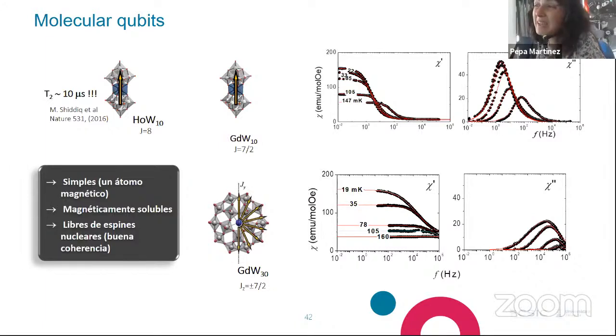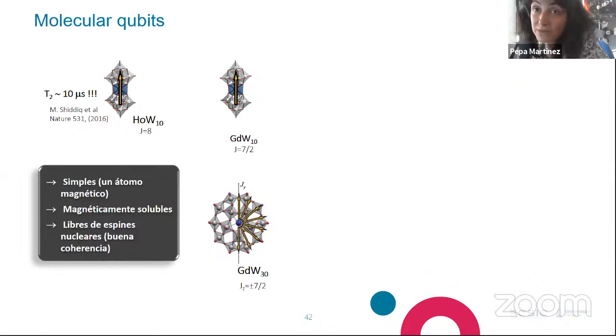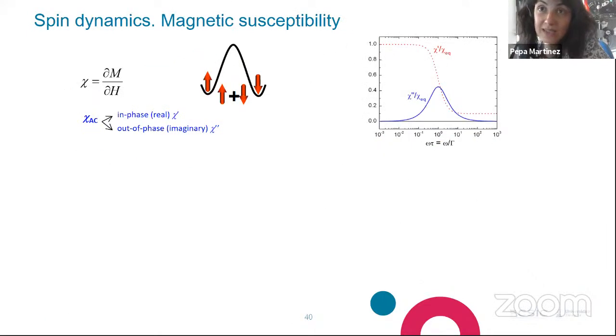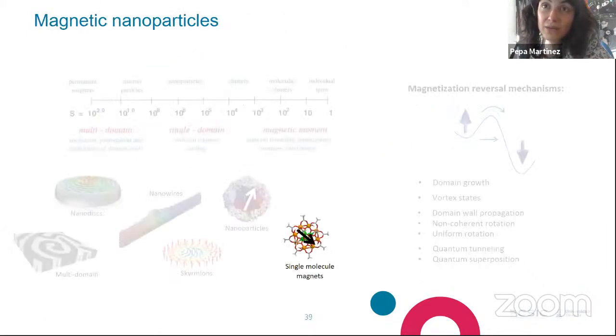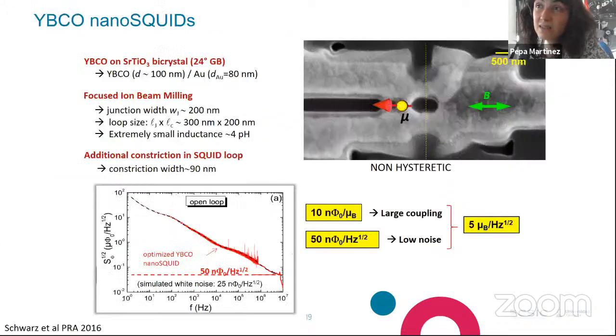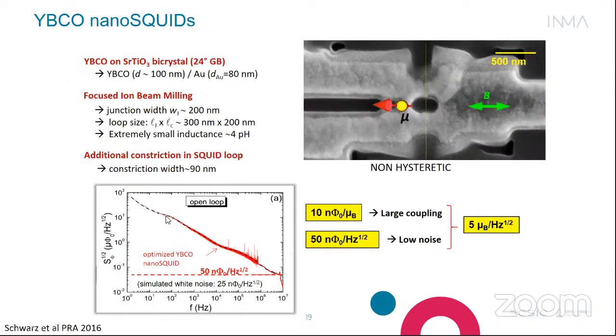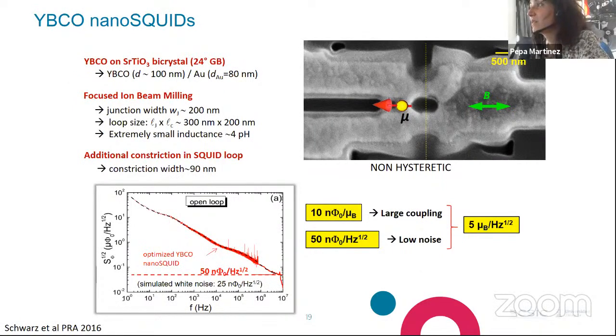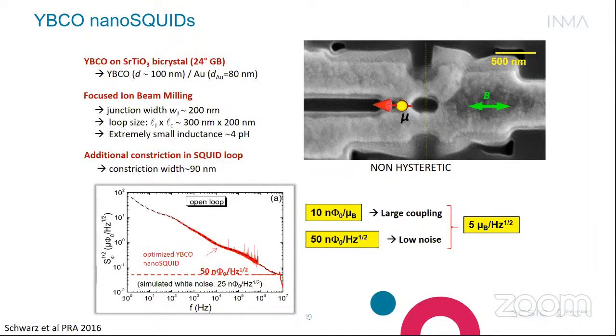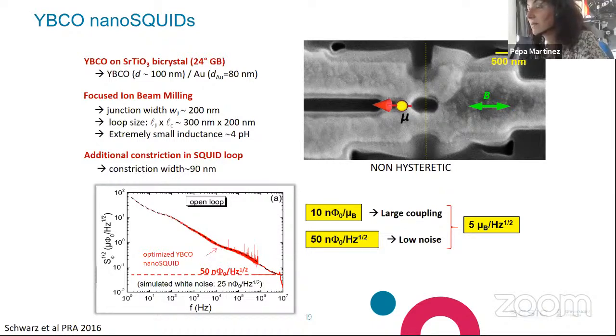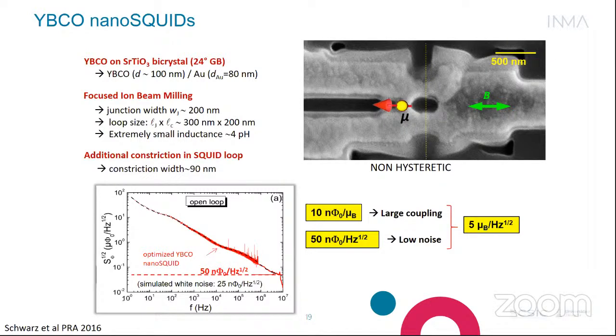Yeah, but also keep in mind that this is only true at very large frequencies, because unfortunately the 1/f noise of this device is quite large. This you can see here. 1/f noise is large in high TC superconductors. So in this case, at low frequency you have about a micro-phi-naught, and at high frequency you are claiming it is 50 nano-phi-naught. Yeah. Okay. Is there any reason why you have such large 1/f noise?